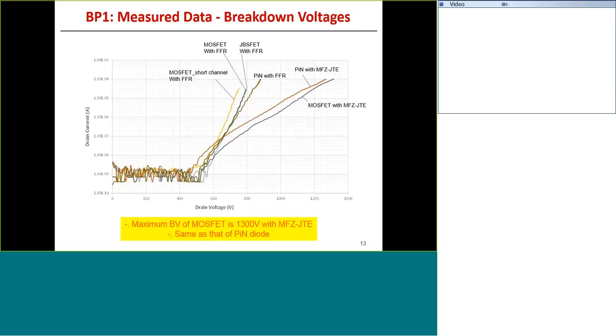In terms of breakdown voltage, we have, of course, measured various devices, and you can see on this graph that the breakdown voltage does depend on the structure and the edge termination. If you look at the graphs in the middle, where the breakdown voltage is approximately 800 to 900 volts, there's a cluster of devices marked MOSFET short channel, MOSFET with FFR, JBS FET with FFR, and PIN with FFR. All of these show similar breakdown characteristics, so we associate that with the particular edge termination we're using because they all had the same FFR termination.